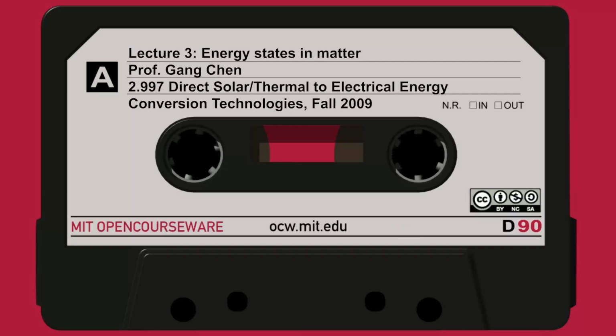You create the energy state. Sometimes even an impurity, even a vacancy, could create those additional states. In silicon, we do artificial doping. When we do thermoelectric materials, a vacancy, the missing atom, could create those kinds of situations. So doping in thermoelectrics is very important. Of course, this is true for all semiconductor devices. Okay. Any questions here?